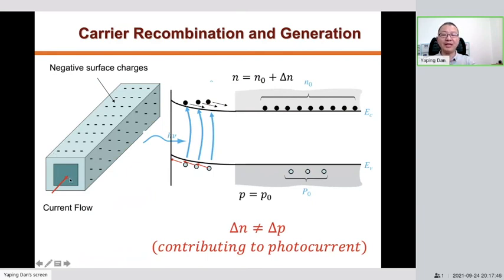For example, in an N-type semiconductor, electrons are the majority carriers, and the surface will be filled with electrons, so they will form negatively fixed charged surface states. These negatively fixed charged surface states will push away the electrons and form a depletion layer near the surface.